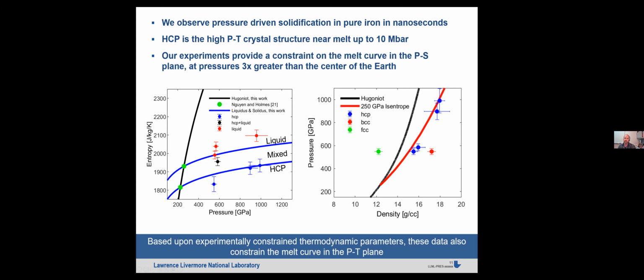But of course, there have been giant impact calculations, and we've mined those to show that, in a statistical space, you would expect that the cores will be completely liquid. But it doesn't say anything about how long it takes to get from, say, 15,000 degrees down to the melting curve at 10,000 degrees or 25,000 degrees down to the melting curve at 10,000 degrees. There's still that unknown amount of time to remove the heat to go from the initial thermal state to the melting curve. Yes, that clarifies it. Thank you very much.